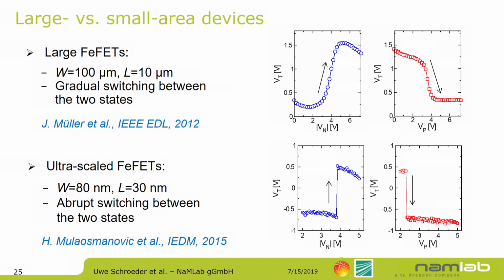So now let's have a look at how small and larger devices behave. If you have a large FeFET, you can imagine you have all your hafnium oxide grains in your transistor structure, and let's think of one grain as one domain. This is the simplest approach. We have all the different orientations of our grains, and slightly different sizes of these grains, so we would expect slightly different coercive voltages for each grain, which means that they all have a different voltage where they switch. That's what you can see here. These transistor devices are 100 micrometers in width, and you need to apply a voltage here ranging from like 3 to 5 volts until you completely switch all your domains within the transistor and switch from one to the other threshold voltage.